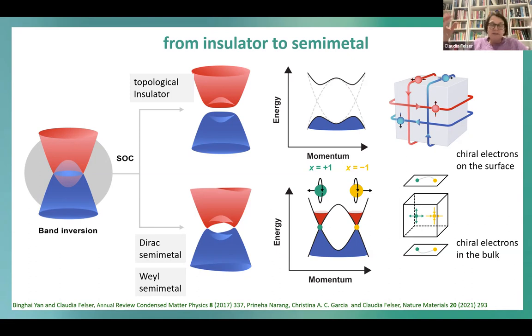So we have this degenerate point, and this leads to semi-metals. We can have semi-metals at high symmetry points, which have a lot of symmetries. This is a Dirac semi-metal, like cadmium arsenide. But if the symmetry is reduced, we don't have inversion symmetry, or if we have magnetism, these crossing points with linear dispersion, which we see here on the right side, become Weyl semi-metals. And they are super interesting because suddenly we even have electrons which are chiral in the bulk, not like the surface state in the topological insulator. So you have these crossing points, like a Dirac crossing, you see the green and the yellow dot. These are electrons in the bulk which are chiral. So they act like a monopole in a magnet. You have a source and a sink.